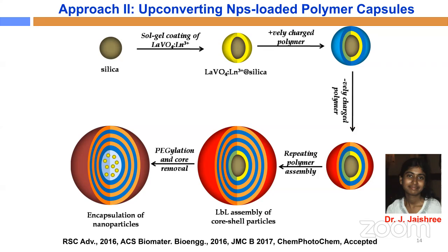So that polymer capsule approach, where the polymer capsule acts as the nano reactor or micro reactor to encapsulate the particle. But the disadvantage that we found is that we couldn't load any hydrophobic nanoparticle, as well as highly crystalline, high temperature nanoparticle, because the capsule gets disintegrated. So Jayashree came up with another alternative approach.